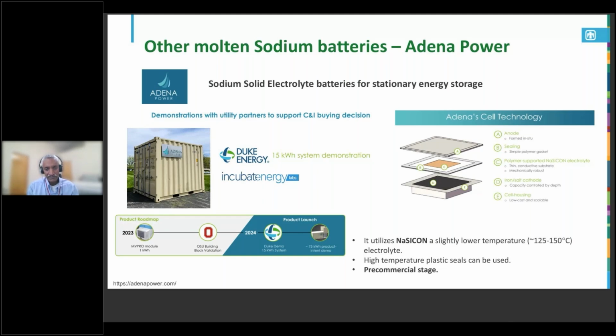solid electrolyte conductor instead of the beta alumina sodium ion conductor, which is high temperature and requires about 300 degrees C for sodium ion conductivity. Nasicon conducts sodium ions at a lower temperature, so about 150 to 125 degrees C is sufficient. The advantage is at this temperature you can use plastic seals. So they're going with a planar configuration and trying to develop these batteries. It is still in the pre-commercial to R&D stage.